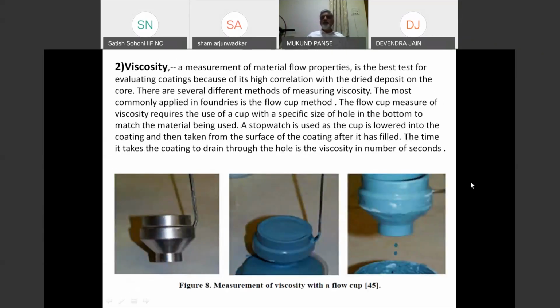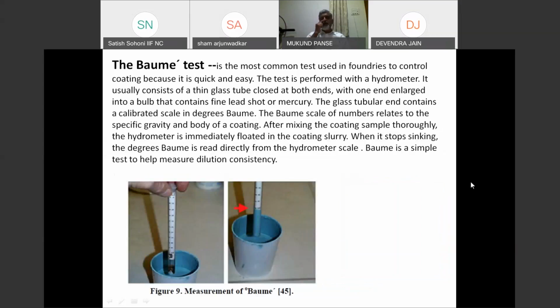Viscosity is measured by flowing through a cup, standard cup. Paint is taken in the one standard cup and paint is allowed to flow through it. A stopwatch is used and the time taken for the paint to completely run out of this cup is taken. It's an arbitrary number. You have to ensure whatever paint you have standardized using, you have to intermittently check the use of it and ensure that the viscosity of the paint is properly maintained, so you are getting the required thickness of the coat.